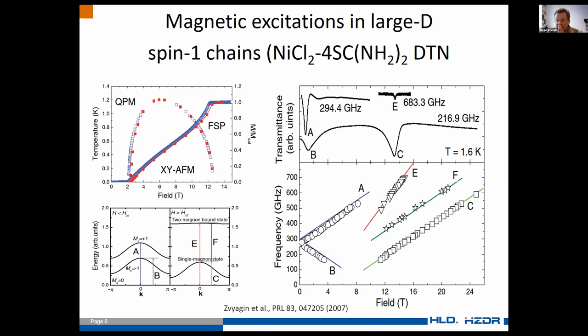And the problem with this material was that people tried to describe the phase diagram, including this BEC state, using different spin Hamiltonians, which were obtained using different techniques. But the problem is again, if you're dealing with quantum mechanical objects, the effect of quantum fluctuations can be so strong that whatever you measure in low field or in zero field will be far away from reality. So to get important information about spin Hamiltonian parameters, you have to go to very high magnetic field where the magnetization is saturated, and then look at the excitation spectrum, and from it you can accurately get the spin Hamiltonian parameters. And actually, this is what we did with this material.